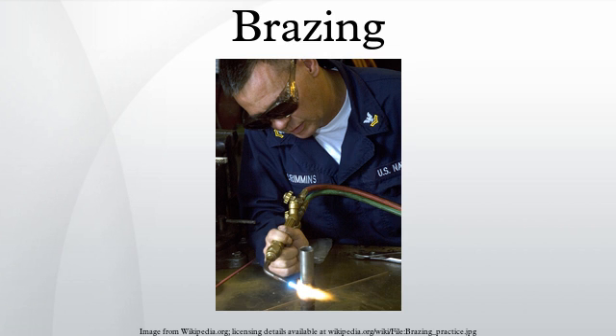Combusted fuel gas: 41 to 45% N2, 17 to 19% CO, 38 to 40% H2. For copper, silver, copper phosphorus and copper zinc filler metals. For brazing copper, brass, low nickel alloys, medium and high carbon steels.